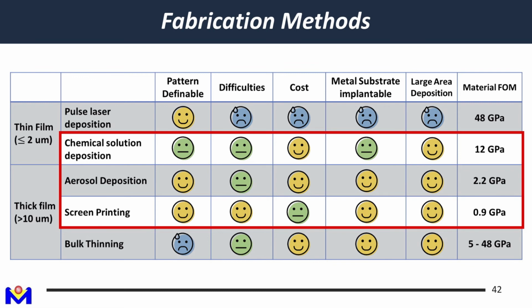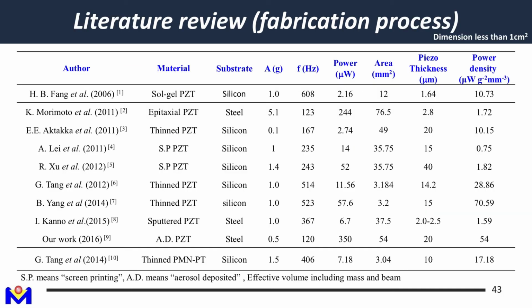So if you want to do thicker film and an alternative substrate like stainless steel or other metals, then you can try aerosol deposition or screen printing. The advantage is it can deposit on different substrates, and it can have a larger piezoelectric effective volume. The cost is also lower. For example, with aerosol deposition or screen printing, you do not need to do the process inside a clean room, and it deposits at room temperature. But of course, the figure of merit, the piezoelectric performance, is worse than CSD, the chemical solution deposition.